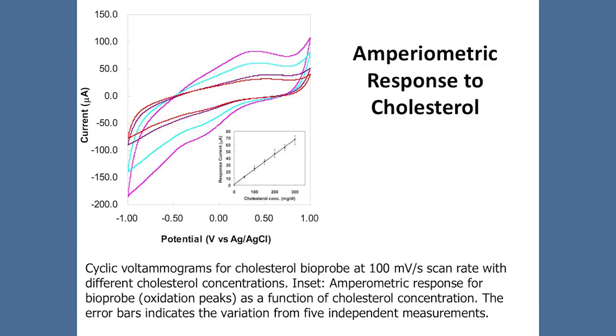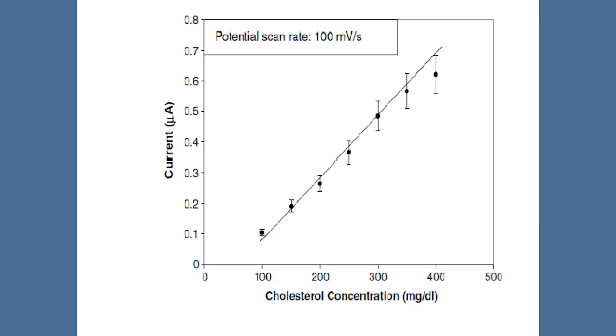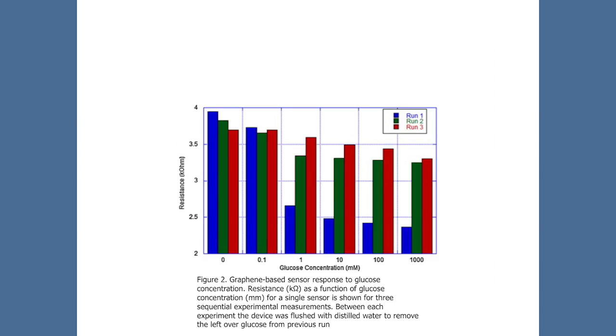This is a cyclic voltammogram for cholesterol bioprobe with different cholesterol concentrations. It is sensitive, but not as sensitive as we would like it to be. This is a graphene-based sensor response to glucose concentration, the resistance on this axis, and the glucose concentration on the x-axis. As a function of glucose for a single sensor is shown for three sequential experimental measurements.